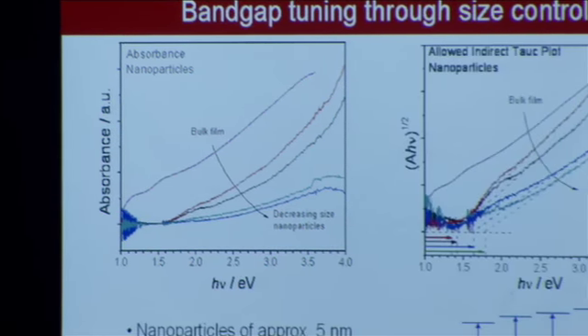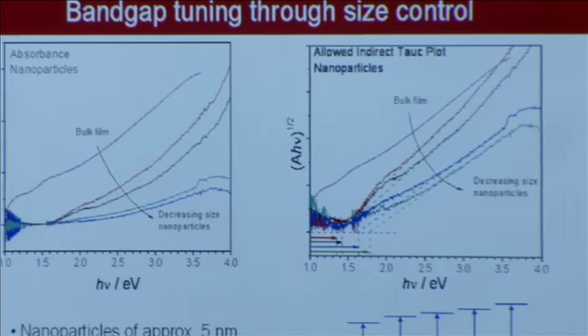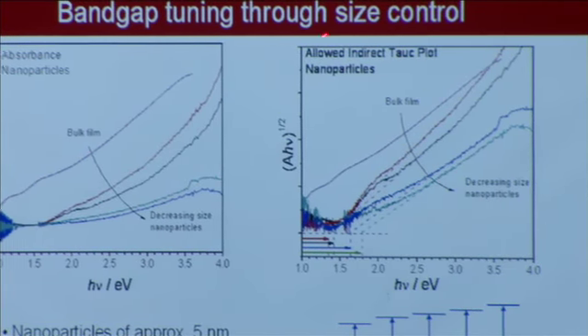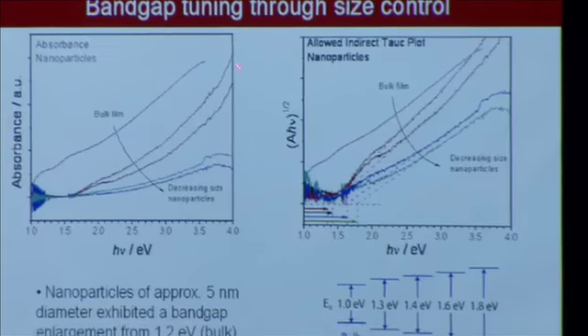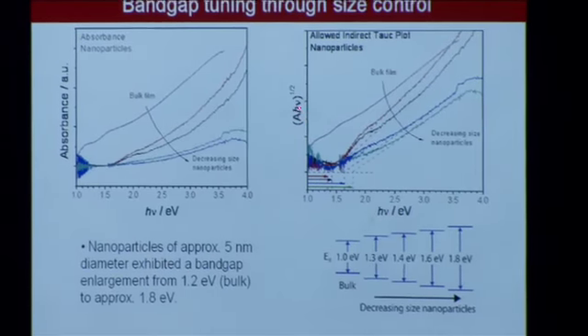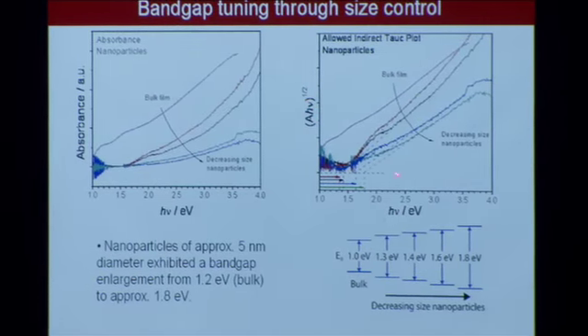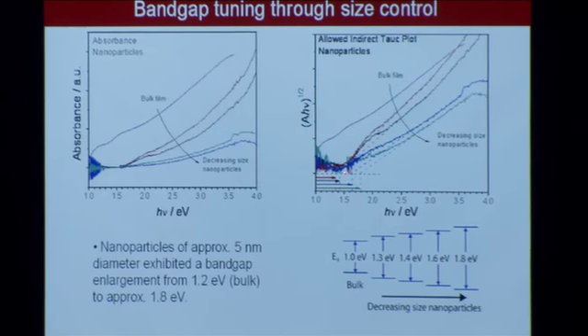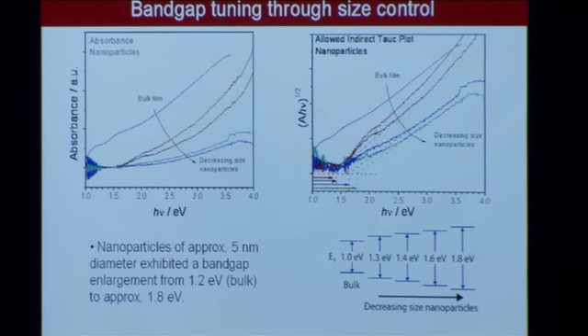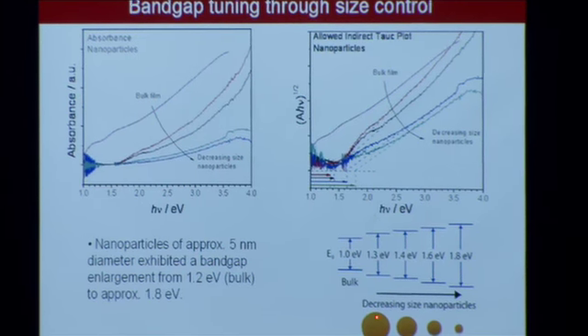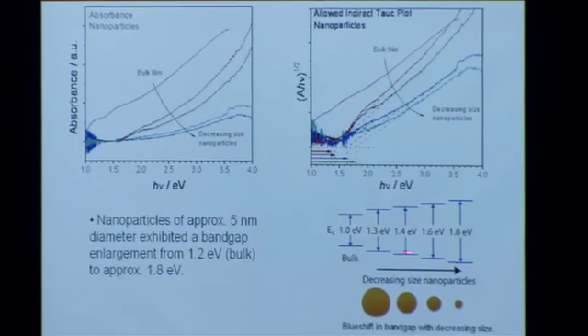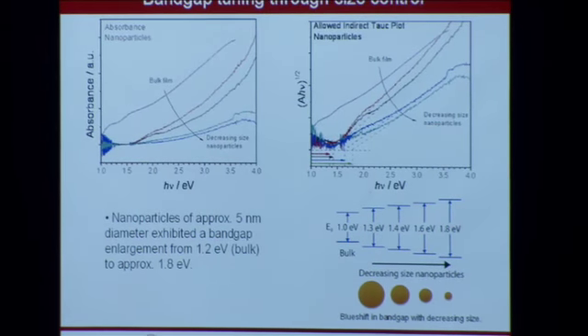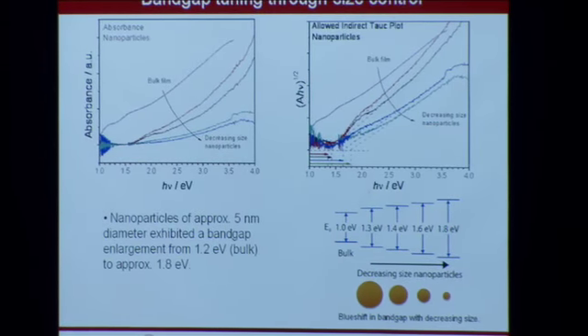So we can take this data, and then the more formal way to calculate the band gaps of these materials for an indirect band gap semiconductor is to make a Tauc plot, which is the absorbance times h nu to the 1/2 power versus photon energy. And you can see here we extrapolate down to retrieve the band gaps of our semiconductors. And in fact, what this data is telling us is that we've quantum confined. This is our measurement from the bulk. These are the nanoparticles in terms of decreasing sizes down to 5 nanometers. We've been able to widen that band gap to 1.8 eV, which is exactly the target that we were shooting for.